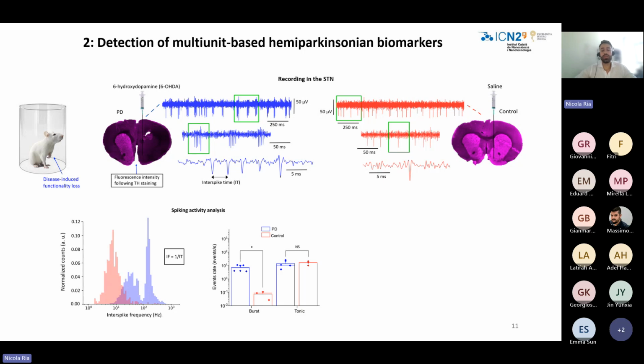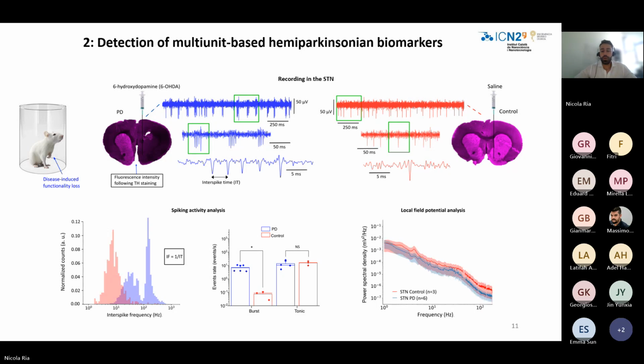This result was quantified across several animals for both groups. And as you can see, there is a significant difference in the presence of bursts between the two groups, while for the tonic spikes, there is no difference. The same analysis was also conducted by looking at the local field potential. And in this case, we were not able to find any significant difference between Parkinsonian and healthy animals. So basically, in the kind of signal that big electrodes can record, it is not possible to distinguish any biomarker or any difference between healthy and sick animals.